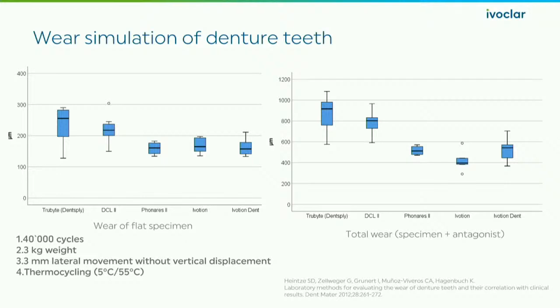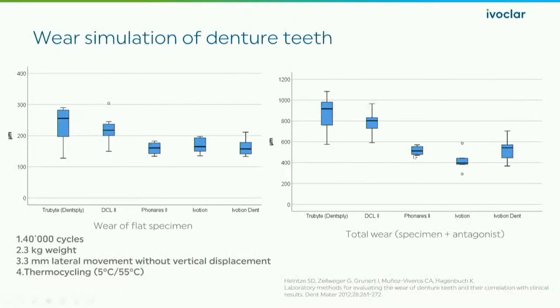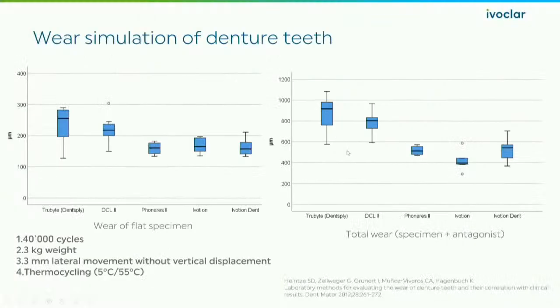You know, of course, you're going to have a wider gap when two materials are being worn when you measure that space in between versus what was lost on the one. But you can see it's a very similar pattern occurring. So we feel pretty confident the measuring is correct. What you look at Phonares here, and being a nanohybrid composite tooth and having that composite shell on it should be very resistant to wear. You now look at Ivotion next to it and Ivotion Dent. You know, they all kind of fall in the same category, but the DCL, that blue line tooth over here, and then the TrueBite IPN sitting over here, you know, with a lot more wear in both instances here.